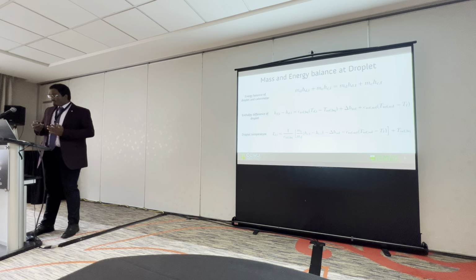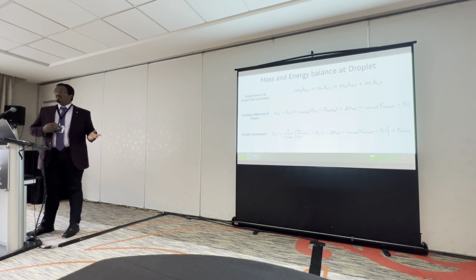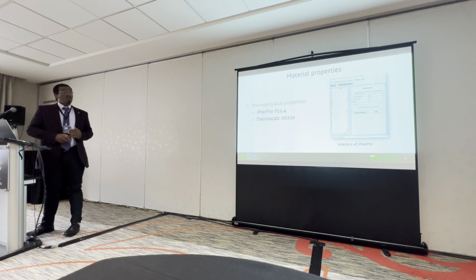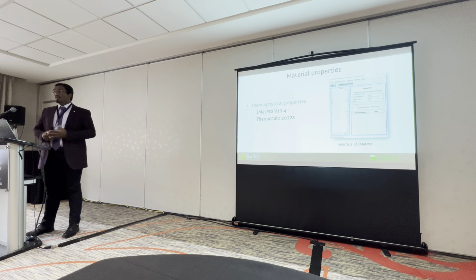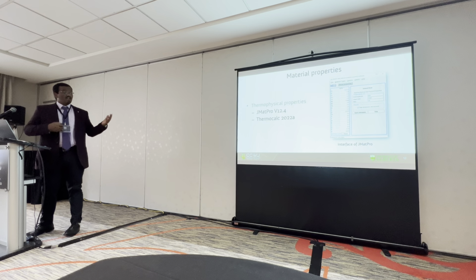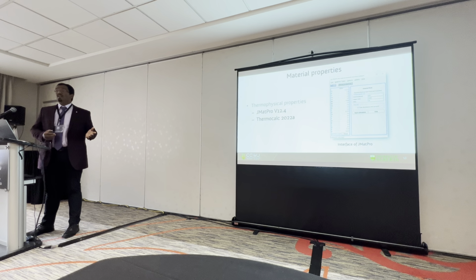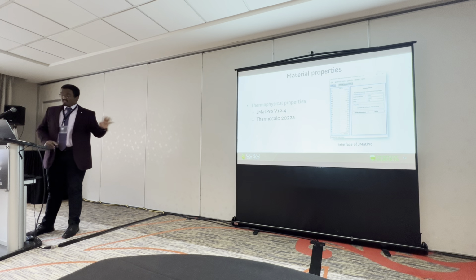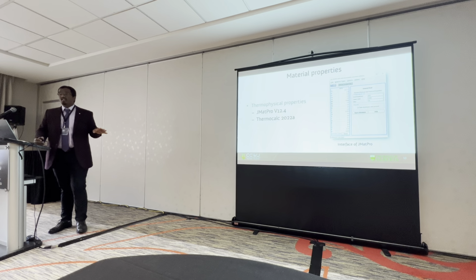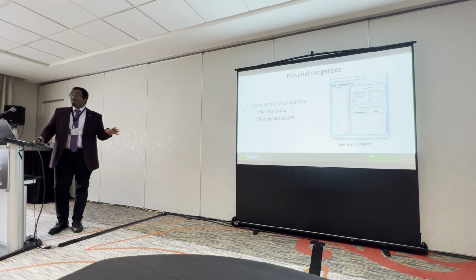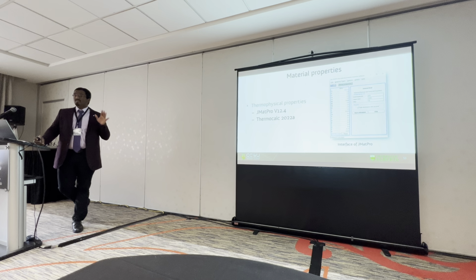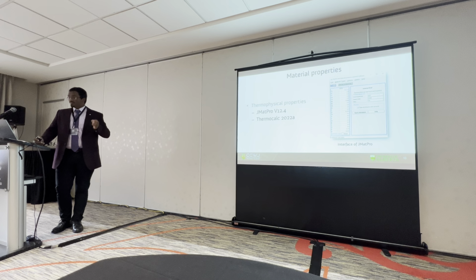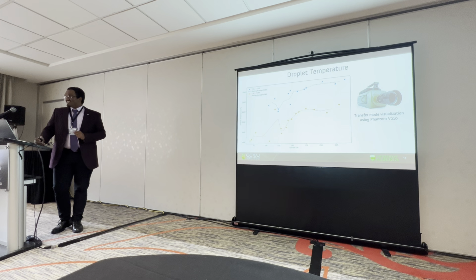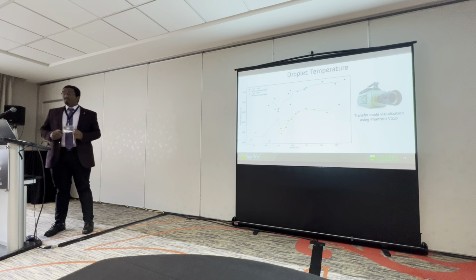Since this requires a lot of thermophysical properties, we obtain all of them using JMatPro and Thermo-Calc. I take the data from JMatPro and verify it with the data from Thermo-Calc. Since I'm using aluminum alloys, I correlate these alloy properties with the ASM handbook for aluminum alloys, and we chose the most representative thermophysical property for each alloy. So we could say that the thermophysical properties would not have a huge error. Based on all of them, we are able to calculate the droplet temperature.